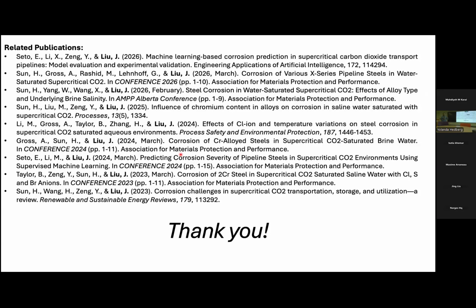So from 2 chromium to P110, which is 1 chromium, and also the X80, for those rates we found an interesting result. They are not like this. Because there has been this debate in the localized corrosion community that you need at least 11%, and 9% is close to it, right? So in order for the chromium to form a full network on the surface, if you go lower, it might even be detrimental. So maybe that is what you're seeing.